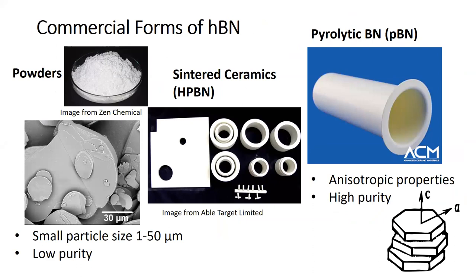And then there's the pyrolytic boron nitride shown on the right, often used for crucibles in MBE systems. PBN has very anisotropic properties, but it has high purity. Typically the C axis, perpendicular to the hexagonal plane, points up away from the surface, but within the planes you have a rotation taking place, so it's not aligned in the planes, and it typically has a very fine crystal structure. So these are the common commercial forms of boron nitride.